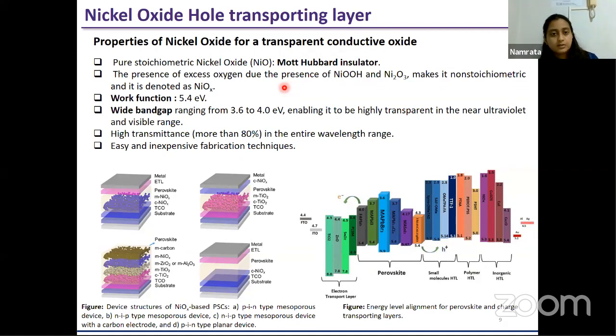The work function for nickel oxide is 5.4 electron volts, and it has a wide band gap ranging from 3.6 to 4 electron volts, enabling it to be highly transparent in the near ultraviolet and visible range. The transmittance of nickel oxide is quite high, more than 80% in the entire wavelength range, and it is easy to fabricate and quite cheap. The fabrication technique required is not as expensive as for silicon.